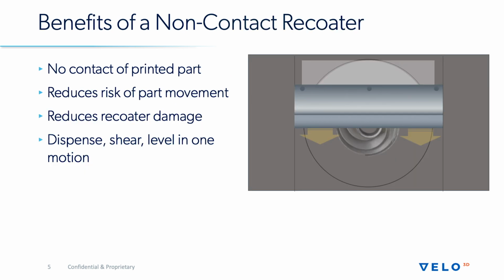So what Velo does differently is we use a non-contact recoater to put the layer of powder down on top of the build. The way this works is that we do a dispense, shear, and level all in one motion, and this happens well above the actual build plane where the part is being printed. Because there's no physical contact between the recoater and the actual part, you no longer have to worry about things like part collisions, moving the parts, or any defects being generated on the recoater. This also allows us to do certain things like having parts be built entirely free-floating within the powder bed, because you no longer have to worry about physically moving the parts as you're doing the print. So this is one area in which Velo is helping to reduce first print yield failures.